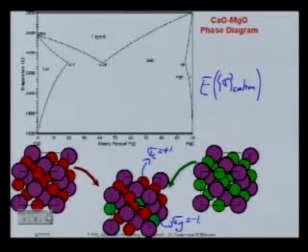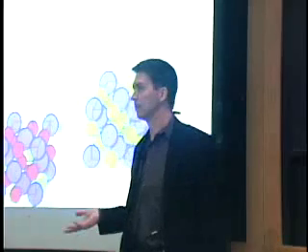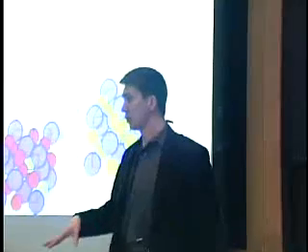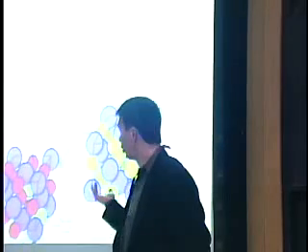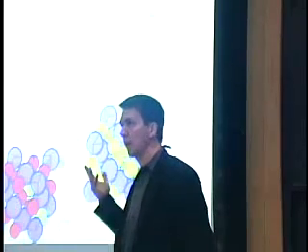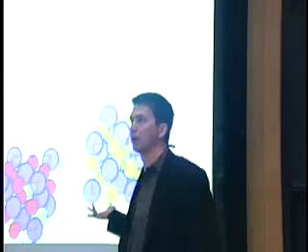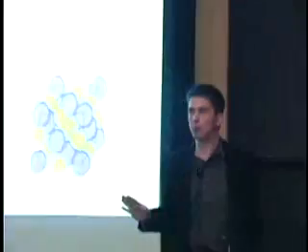And that makes sense. There's nothing unknown about the anion sites. They're always fully occupied. The anions will show up when you calculate the energies of these configurations, of course, but there's no need to expand the energy in their occupation variables because they're always there. They're always -1. So we're going to end up with an effective Hamiltonian between the cations that includes the energetic intermediary of the anions without explicitly including them.